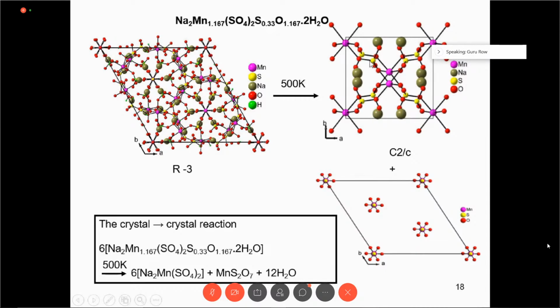The polycrystalline phase was identified by powder diffraction studies as MnS2O7. This is something very unique because MnS2O7 does not occur in nature as such. So obviously MnS2O7 was found during the mineral evolution. So effectively we can also trace the path. If we reverse this path, take these two, and create the temperature and pressure conditions which existed in the terrestrial conditions of those days, we would have formed this mineral.